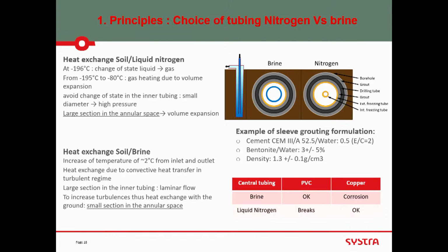In terms of corrosion, we have the brine and liquid nitrogen. For the brine, PVC is okay for the annulus, so the blue one. For liquid nitrogen, PVC breaks because the temperature is minus 190 degrees. And the inner pipe, for central tubing, copper: for the brine there is corrosion of the copper, while it is okay for liquid nitrogen.